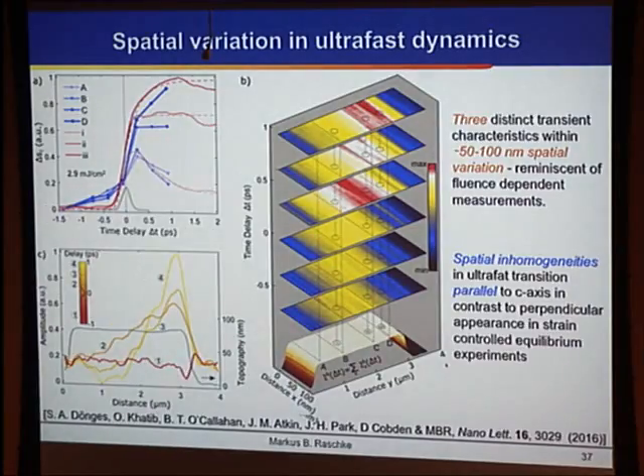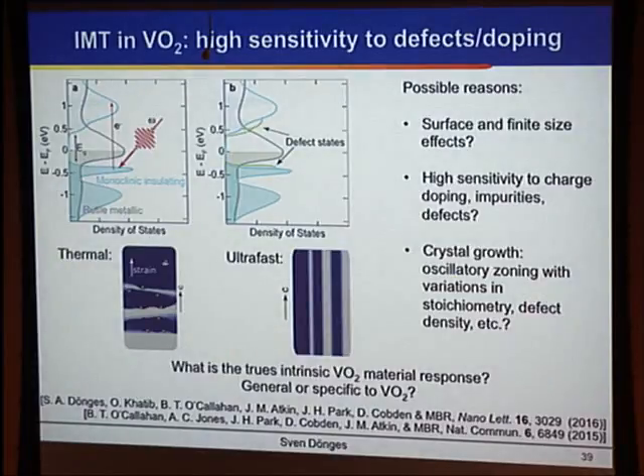And so the other interesting effect is, in fact, that these domains, as they emerge in this case, are in a different crystallographic orientation than in the thermal-induced transition. And so what this really tells us is that this distinct behavior of domain formation in thermal versus ultrafast transitions is really that there are fundamentally different mechanisms occurring, which both give rise to a spatial heterogeneity. We are thinking that in the thermal case it's more a strain control, whereas for the ultrafast transitions, on the order of a few tens of femtoseconds out to picoseconds, it's because we have oscillatory zoning with very small variations in defect concentration in these crystals, which is then, depending on how you define the crystal axis, parallel to the c-axis.